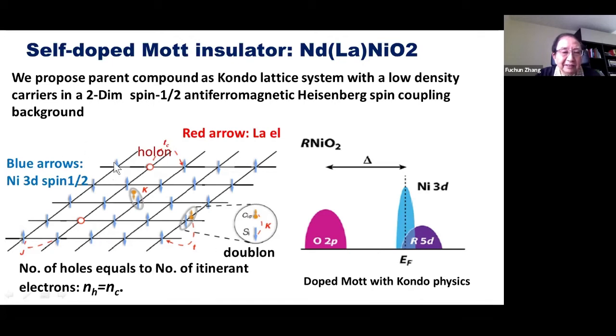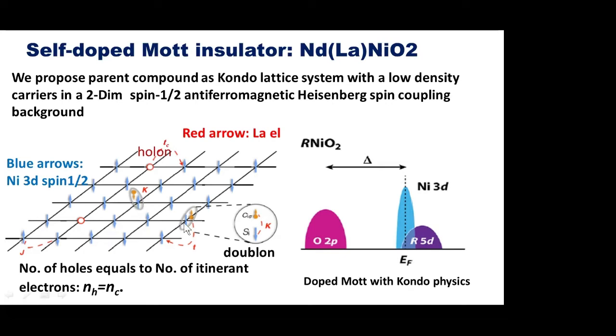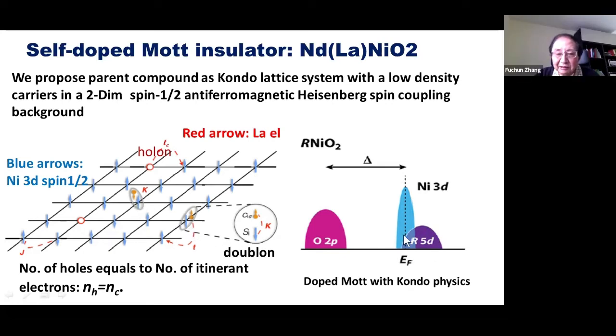For every nickel site, I have either spin up or spin down. The reason is they don't like to have two electrons or no electron because of Coulomb repulsive interaction. However, I have this conducting electron coming from the rare earths, and they interact with the nickel local spin to form a Kondo singlet. Like this one, it's a Kondo singlet. The red ones are lanthanum or neodymium electrons, so they will be captured by the local moment.